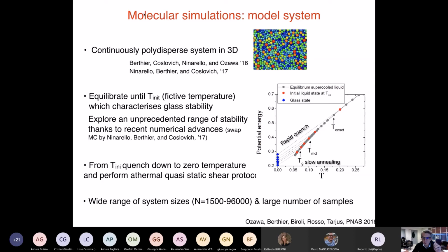I'm sorry that I'm not able to use the arrow to indicate, but in the figure that you have, you have the green line, which is the behavior of the energy as a function of temperature in equilibrium. And then you can equilibrate the system at many different points, even below what is called TG, the experimental glass transition temperature. And from that point, you do a quench at 0 temperature to get the solid state. If you start from a point which we call T onset, and then quench the system to T equals 0, you get a system which is not very well annealed, and that we think is very disordered.